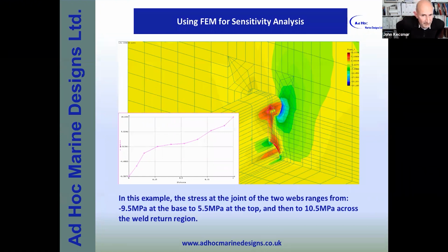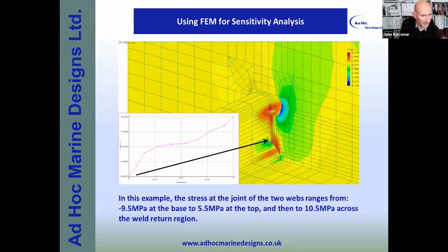Here, this is an FEA analysis I did with a bulb bar running through a transverse frame. And I wanted to have a look at the stress distribution between the welded joint of the transverse frame to the weld, to the shear of the bulb bar. We can see here that at the bottom there was a compressive stress of 9.5 MPa, and all the way at the top it went to 5.5 tensile. Then as the weld goes around the top, there's a peak of 10.5 MPa. So that seems fair enough.